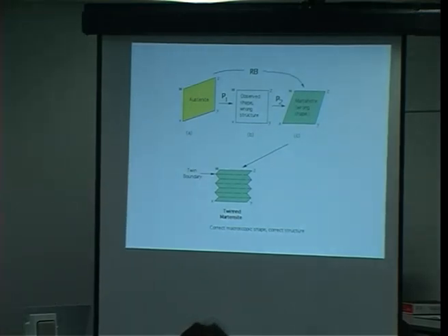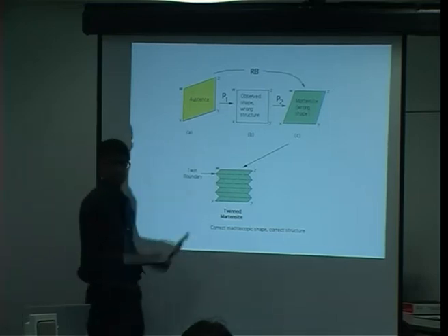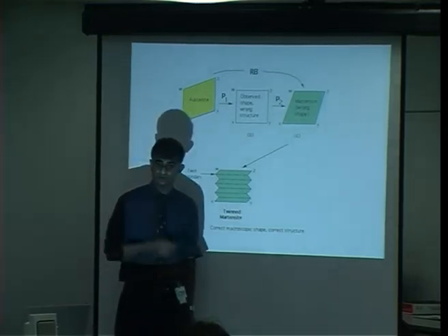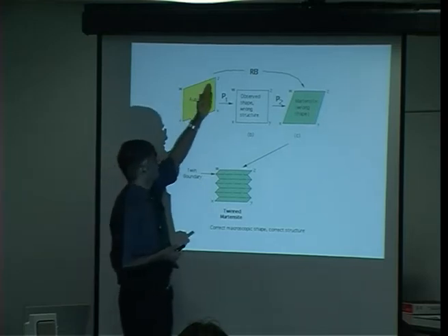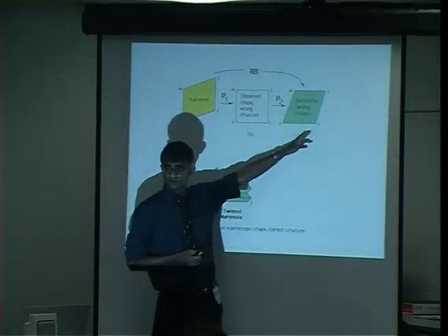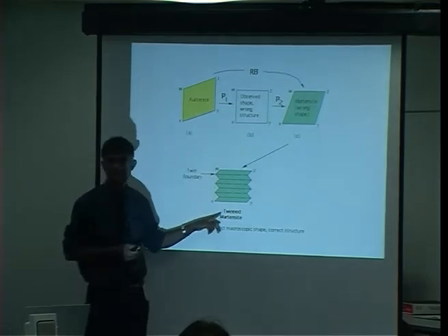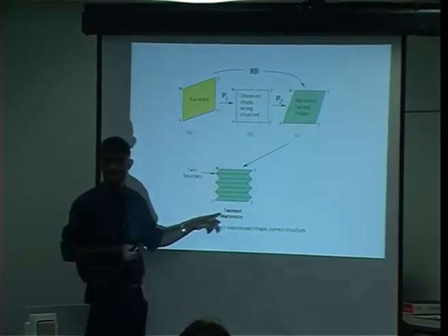So we are adding a deformation which is called a lattice invariant deformation because it doesn't change the crystal structure, but it corrects the macroscopic shape. So what this predicts is that we should see twins inside martensite. So this is a prediction. Furthermore, it explains the strange habit planes that we see. Because even if these planes are rational planes, the average plane here is not. It depends on how much twinning we put into the system.